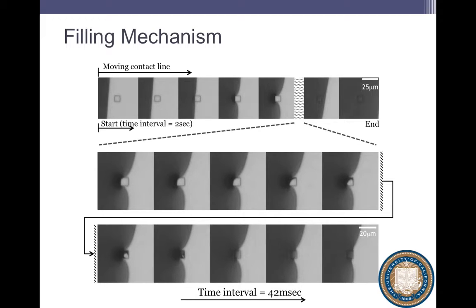And then if you use a high-speed camera and zoom in and see what happens, what you actually find is it fills the cylinder through a capillary filling process. So it moves along the contact wedges, it moves along the corner to fill the cylinder. Now, what is it doing, therefore? It is going in to fill the cylinder, and it's pushing the air out.